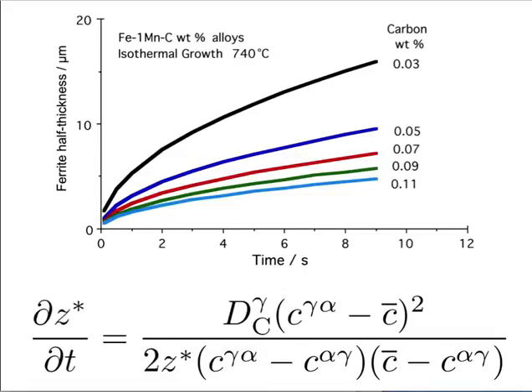This is really important because in order to get toughness in structural steels - bridges and so forth which are welded - you always aim for low carbon concentration; 0.05 carbon is typical. If you make your steel with 0.04 carbon instead of 0.05 that makes a big difference to the structure. These huge quantities of steel are produced to very accurate concentrations - even if you are producing 100 million tons you have to control the concentrations to that sort of accuracy, and that is done.